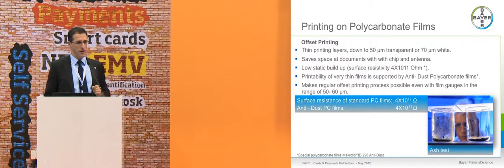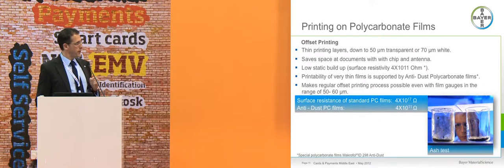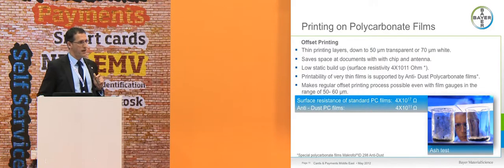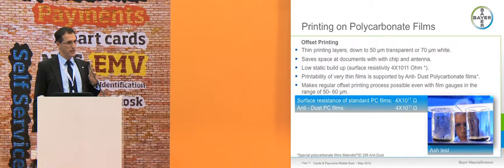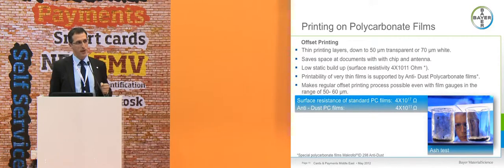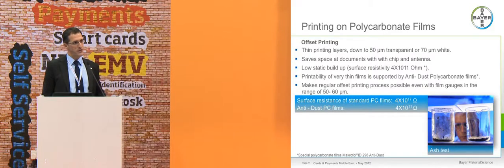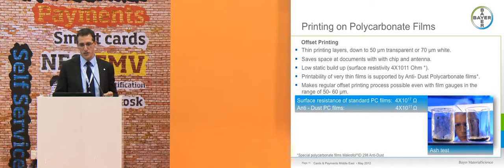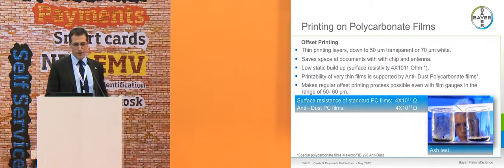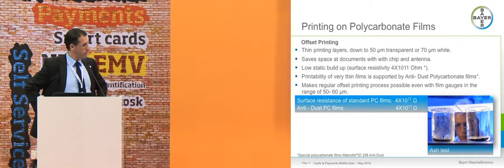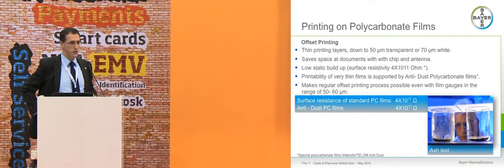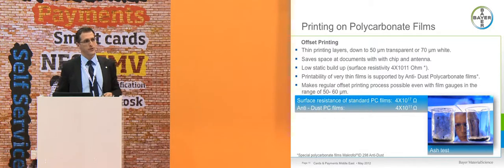There are special polycarbonate films available from Bayer, which allow printing on them even in thickness ranges around 50 microns. How does this work? These films are specially treated by Bayer by putting additives into them that make the film anti-static, so it has a higher surface electrical conductivity. That allows the offset printing machine to be fed very easily without static build-up, so the film will not get stuck in the feeding unit of the machine, and you will get a very good printing result. As you see there, the anti-static polycarbonate films go down to a surface resistivity of 10 to the 11th ohm, where the standard films have a surface resistivity of 10 to the 17th ohm.